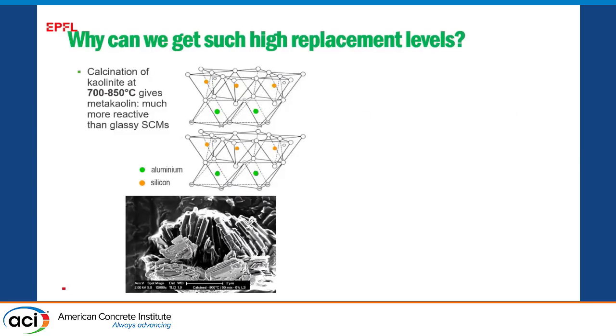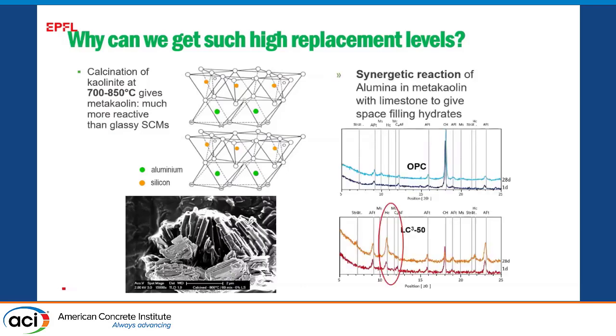And why do we get this synergetic reaction? Because we're using clays that contain some kaolinite, which has this one-to-one layer structure with a layer of silica and a layer of alumina. And when you heat it up, this becomes disrupted. Both the silica can react in the pozzolanic reaction, and the alumina can react in this synergetic reaction with limestone to give us these products we call carboaluminate. They're actually there already in Portland limestone cements, but we've got somewhat more of them in these blends.